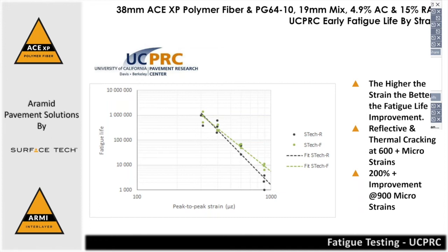we talk about a fatigue number, and typically it's done at one strain. If I'm looking at what's at the bottom of a pavement, it's way off to the left, probably below 80 microstrain. The moment you get above 100, that's when you begin to see alligator cracking on pavements. A lot of the things we miss is just general brittleness and fatigue of a pavement that could happen at the surface too, where block cracking happens.